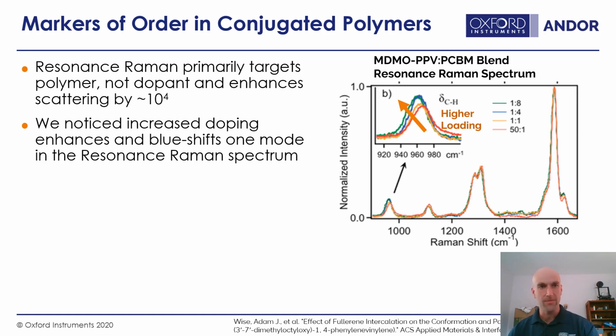So resonance Raman, like I mentioned, primarily targets the polymer in this case because we're exciting in the visible on or near resonance just with the polymer, just with the donor, not with the acceptor, not with the C60 derivative. It enhances the scattering by a factor of about 10,000, give or take, which is pretty great in terms of our ability to generate a decent amount of signal from a fairly small illuminated spot when we're doing mapping or things like that. More importantly, we noticed one particular Raman peak was increasing and blue shifting disproportionately in the resonance Raman spectrum as we loaded in more and more dopant.